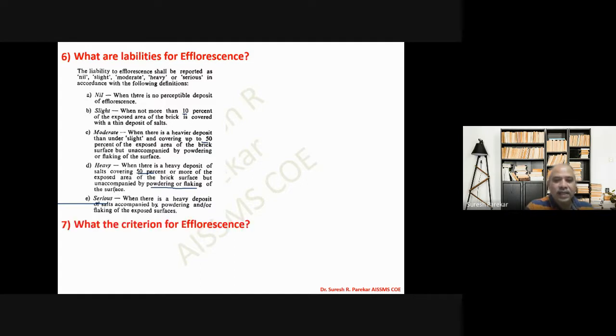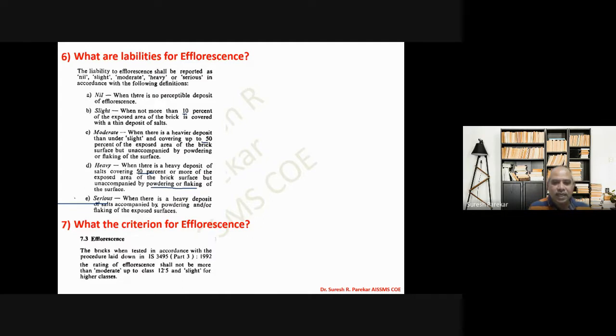Now, what is the criteria for efflorescence? So that is clearly given, that rating of efflorescence. This is given in IS 3495, and that is given the rating of efflorescence shall not be more than moderate up to class 12.5. So up to class 12.5 shall not be more than moderate, means we can have up to 50%, and slight for higher classes, means that is allowed up to 10% for higher classes. So that we have to check. If that criteria is not satisfied, we are not going to use those bricks.